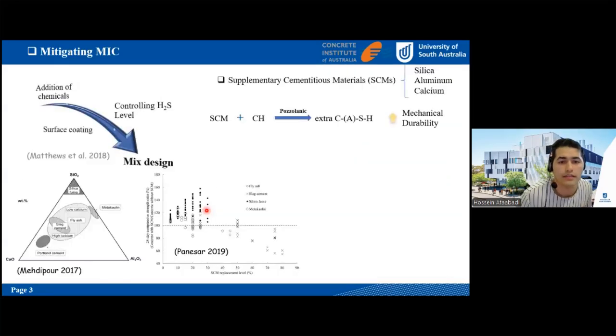In order to mitigate MIC in this environment, a lot of research has been done over the last decades, but one of the most effective methods is to improve the mix design of the concrete that you are going to use in this environment. Different methods like chemical additions, surface coating, or even controlling the hydrogen sulfide gas level in the system have been tried, but all of this concluded with improving the mix design.